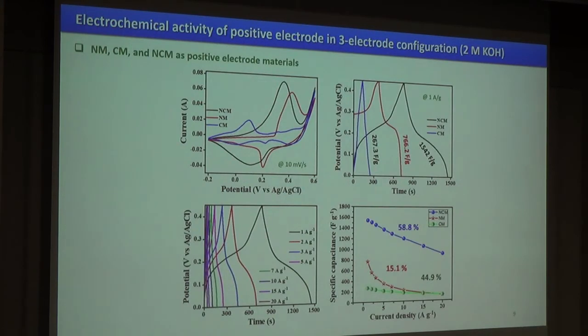Now the energy storage activity of these materials was studied as positive electrode material in 2 molar KOH solution and 3 electrode configuration, and we observed that NCM shows the highest specific capacitance, and from the rate capability we observed that CM shows better rate capability than NM, but in the combination of these two materials, that is in NCM, we observed much better rate capability.